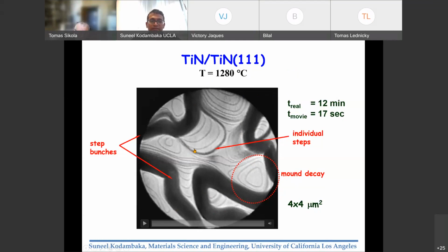What you're looking at are these single atom height steps. Well, technically for titanium nitride 111, it's not a single atom height, it's a bilayer, because titanium nitride 111 is a polar surface. So you have individual layers made of the same type of atom, a titanium atom layer and a nitrogen atom layer. So each of them is a bilayer of titanium nitride.